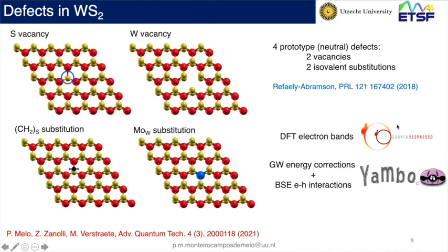Okay. So the question is, hello Pedro, what concentration did you use for the vacancies? Hi, Nick. This is one vacancy in a 5x5 supercell. I can't give you the number exactly. The 3x3 is too low, especially for the W vacancy. The defects will start interacting, and the 5x5 is the minimum that you can have to have an isolated vacancy. Okay, thank you, he says.